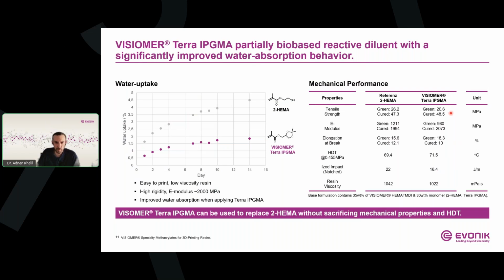So when comparing the Terra IPGMA with the HEMA in the same formulation, the resulting cured material properties exhibit very similar tensile strength and E-modulus, elongation at break, and heat deflection temperature. So again, in other words, the substitution of the HEMA by the Terra IPGMA can be achieved without sacrificing the overall mechanical performance of the printed part.